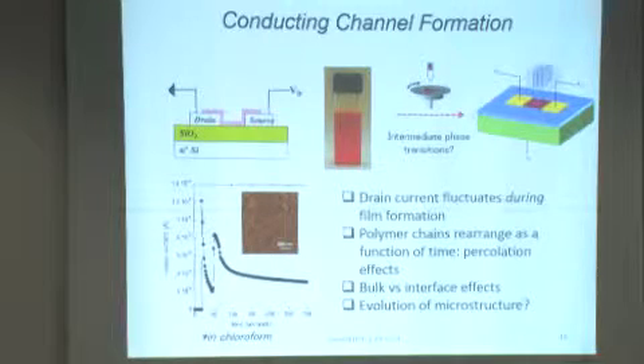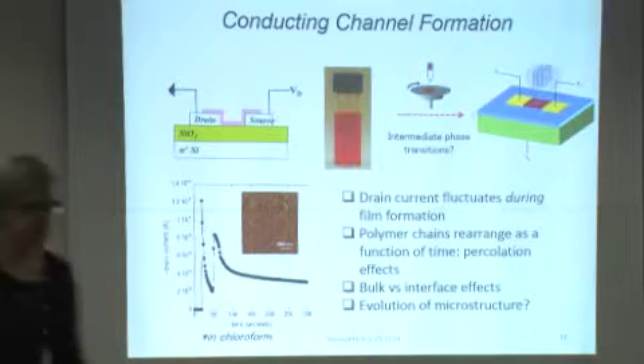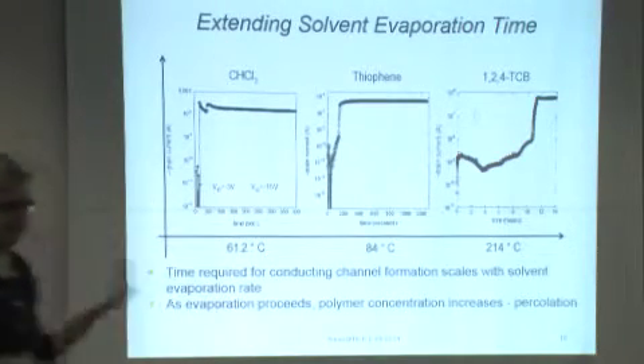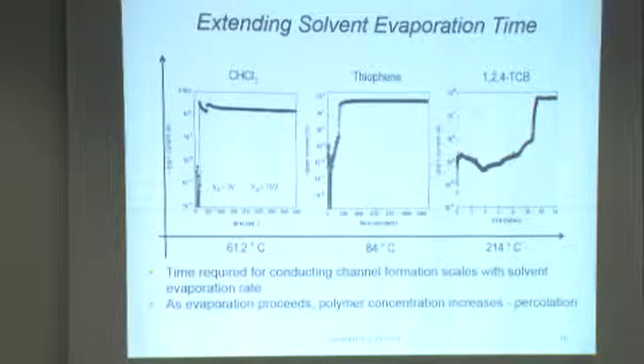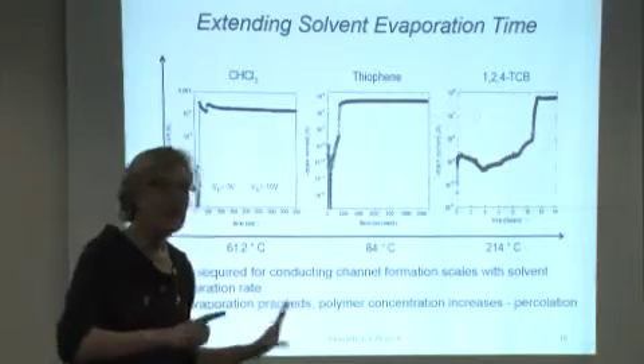All right, so we noticed as we deposit a droplet of P3HT on the surface, drain current fluctuates during film formation, there are percolation effects over time, and microstructure evolves. If we change solvents and extend the time, you see differences with solvent, but they're largely associated with changes in the boiling point or vapor pressure of that solvent. And evaporation rate certainly does affect things, but it's not clear exactly how.